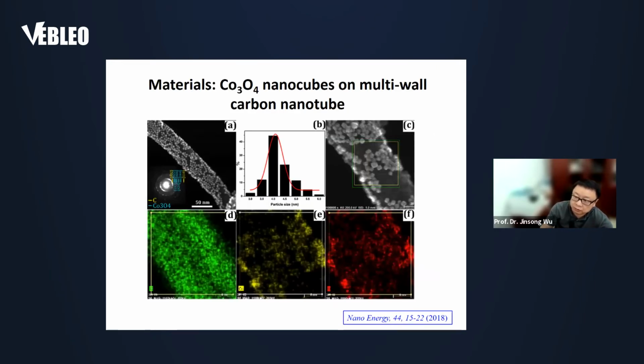And the second sample that we use is the nanocubes. We can also load them onto the few-layer carbon nanotubes. And you see here's a small view and here's a larger view of the oxide cubes on the surface, on top of the few-layer carbon nanotube. And here's the EDS mapping, and it shows that we have a good sample for our test.